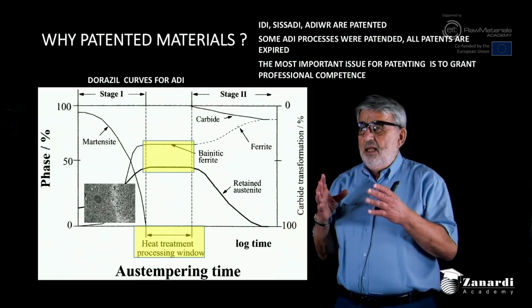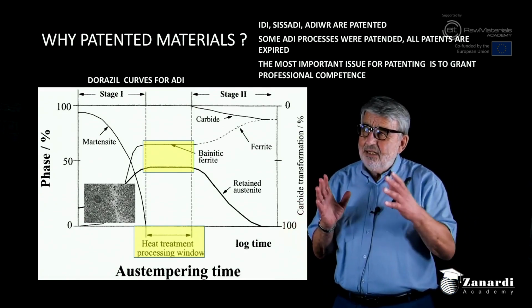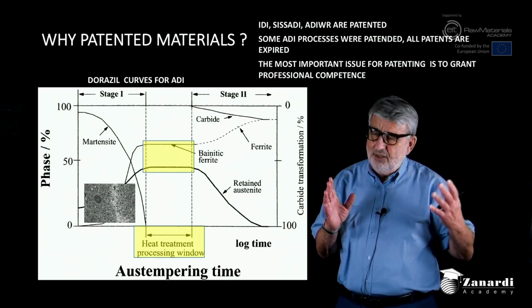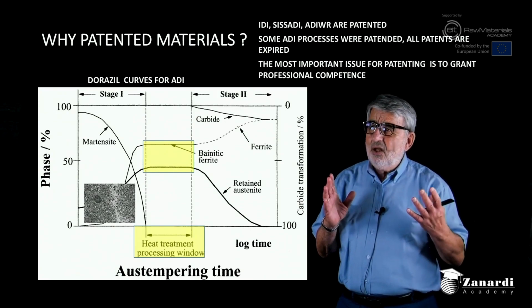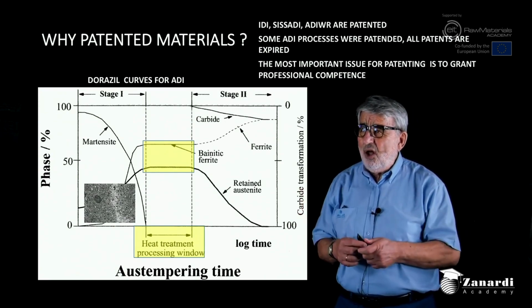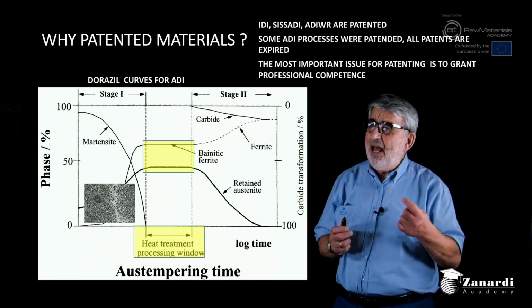But the time needed to complete this reaction depends on the distance between two nodules and depends on the segregation pattern we have.